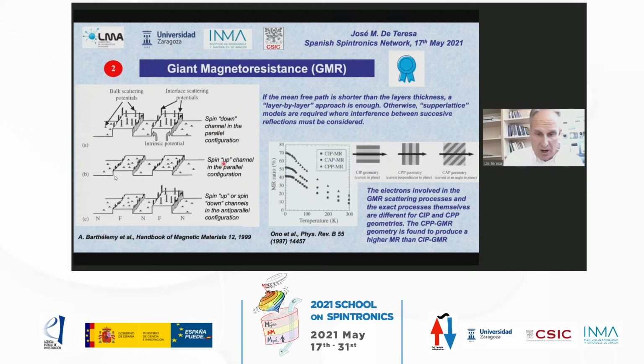Now, if you take into account the potential seen by the spin-up channel in the parallel configuration, in this case, the potential will be lower in the ferromagnetic layers and also for the magnetic impurities. And for the spin-up or spin-down channels in the antiparallel configuration, there will be an alternation between the potential in the ferromagnetic layers when they find the parallel or antiparallel ferromagnetic direction. Okay, good.